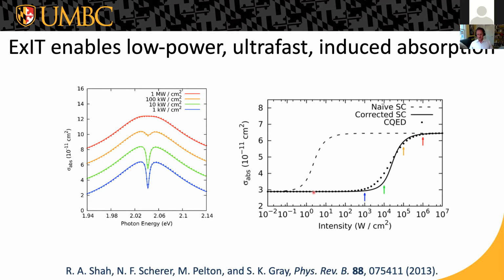But the saturation now, which is a weak nonlinearity in the quantum dot because of its small transition dipole moment, is amplified by about 4 orders of magnitude by coupling to the much larger dipole moment of this plasmonic system. So you can get very large changes in the absorption cross-section at relatively modest optical intensities. These are not maybe the smallest optical intensities, but it's worth remembering that the footprint of this device is very small, so the actual amount of power that you would have to put in to get this modulation would be